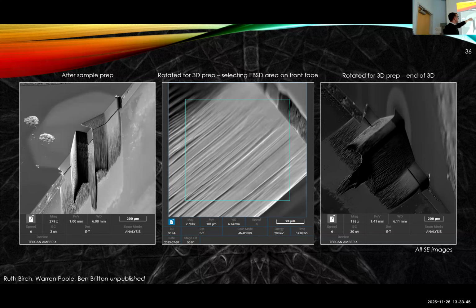So this is how we set up the experiment. We go towards the edge of the sample for this particular example. We create some space so all the diffracted electrons can escape towards our detector. We then look at this surface, and this is what it looks like. You get little, what we call curtains in this case, due to the surface hardness with FIBbing. And then after you have done the 3D, your sample has vanished into the ether because you FIBbed it away. So it's a destructive technique in that case.